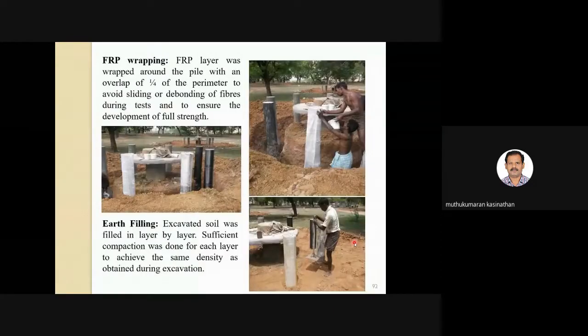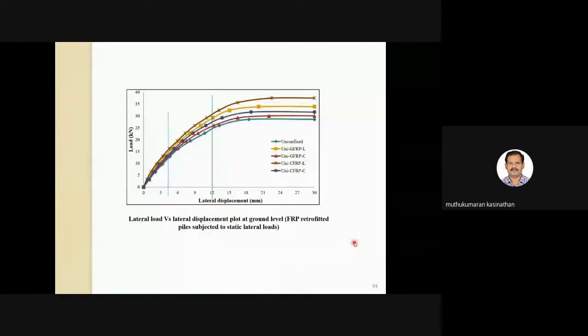Strengthening was done and the test was conducted. So you can see here, if you have noticed closely, the strengthened pile load deflection response and the retrofitted pile load deflection response: the bandwidth, the gap between these responses, is slightly higher in case of the strengthened pile, where the strength enhancement is very high. Whereas for the retrofitted pile, the gap is very, very minimal. So there will be a slight strength increment because the pile is already subjected to 85% of the ultimate load. It is on the verge of failure.